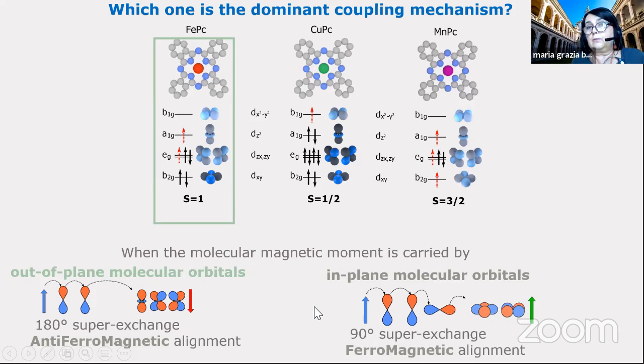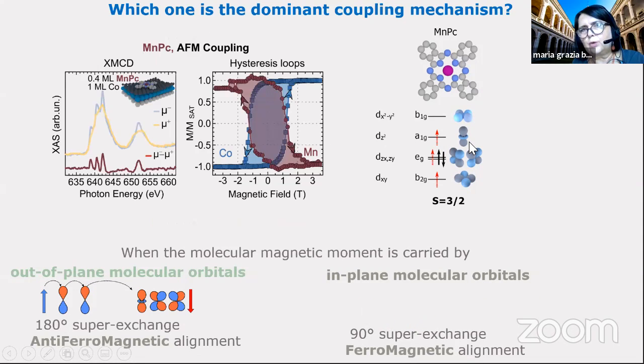So then we can study the third molecule, the manganese. The manganese is more complicated. As you can see, these orbitals are out of plane, these are in plane. But the out-of-plane ones dominate. Also in this case, you will have an antiferromagnetic coupling.